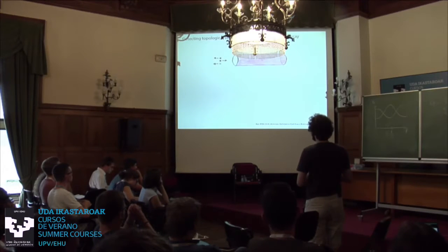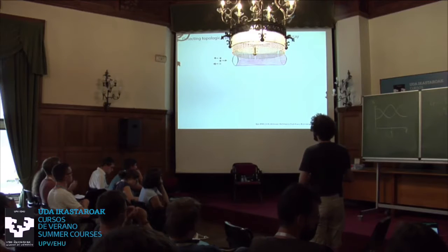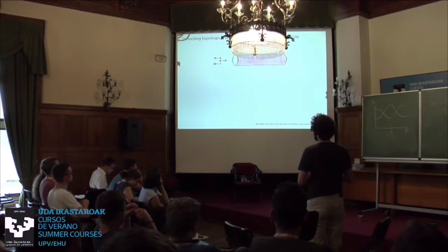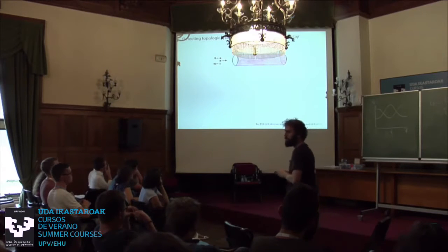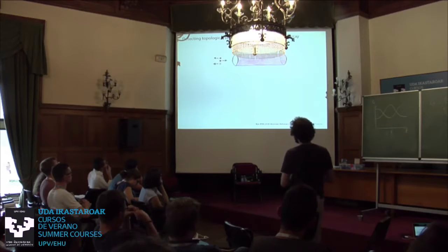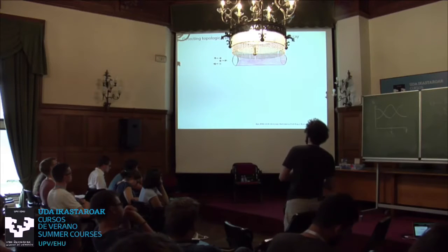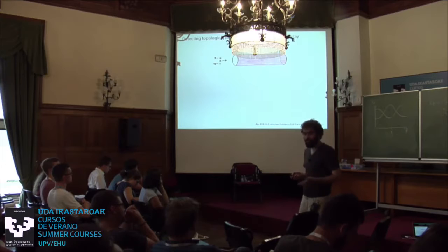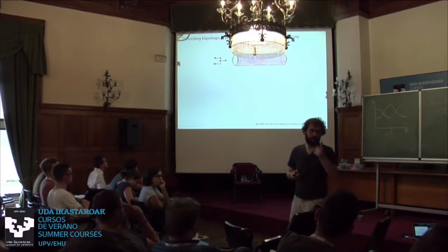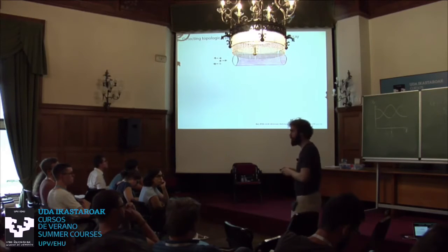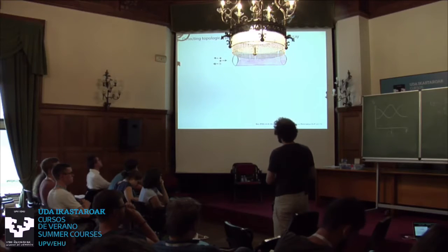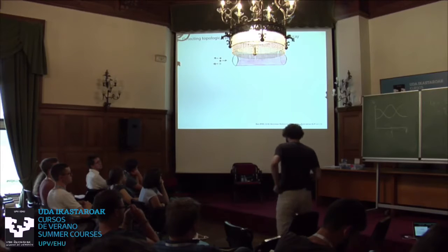So I have now this superconductor, and I want to send in an electron. Now, as this electron bounces off the superconductor, it can either bounce back as an electron or as a hole. If it bounces back as a hole, that's what is called an Andreev reflection. Now, how can an electron bounce back as a hole? Well, in the superconductor, there's a condensate of Cooper pairs, and I can always just add a Cooper pair, which is 2 fermions, and then the fermion count is correct. So if this fermion goes in, then I can take out a hole if I remove a.